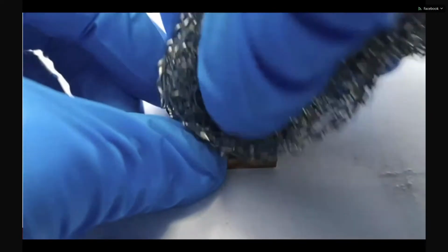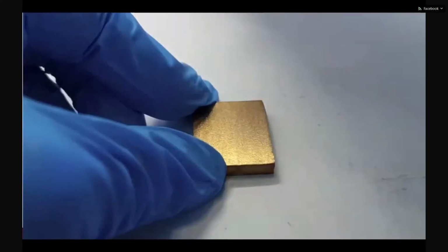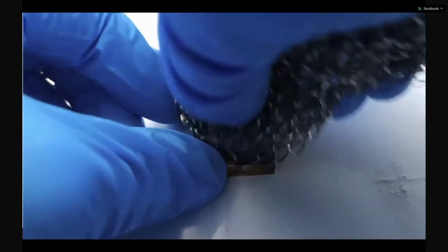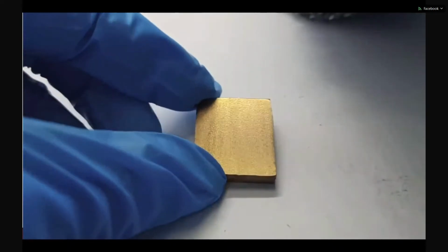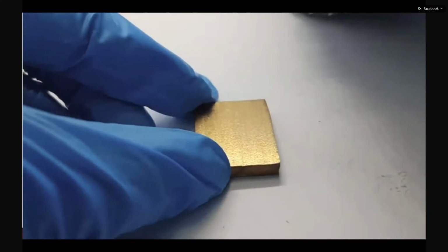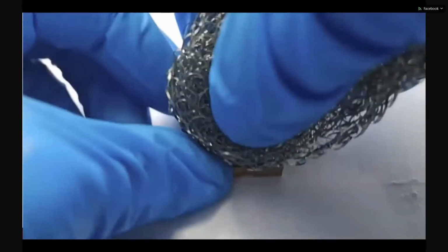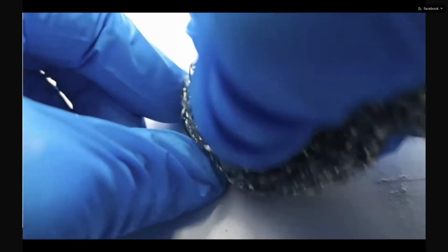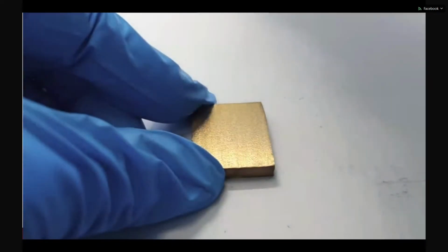So here's a demonstration just using a steel wool. And we can see that if we try to scratch the surface, we actually did not create any scratches on the surface. In fact, it was the steel wool that was damaged during this test.